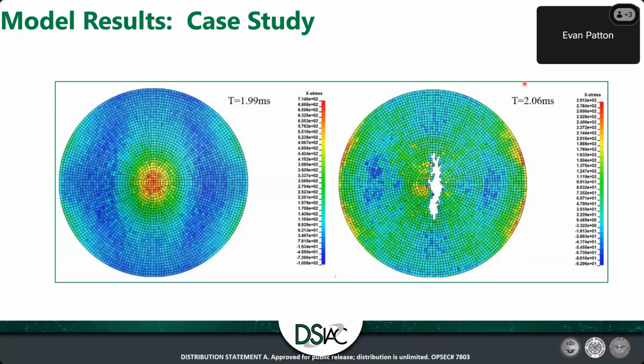And then a few milliseconds later, that stress limit's reached, and that strain limit is also hit, and essentially starts eroding the middle of that composite, and thus completely eliminating all composite, quote unquote, in that area. Realistically, this section is going to be intact in the actual specimen, but for the model's sake, this void area is the damaged area. This is the non-load bearing structure, and so forth.